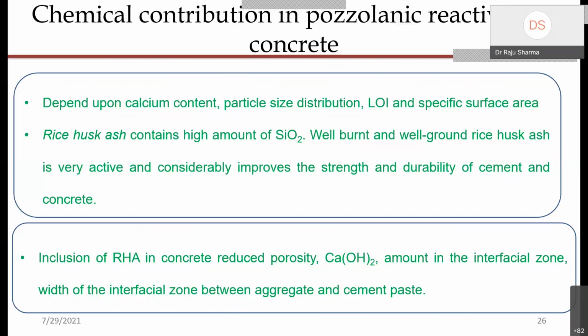When your ITZ is not there, the weak phase is not there. When the weak phase is not there, the early crack formation under loading will not occur. And if it will not occur, the composite can retain higher strength, can retain higher load, right? And produce more hydration product, right? So this is all the philosophy difference between the ultra high strength and the normal strength concrete.